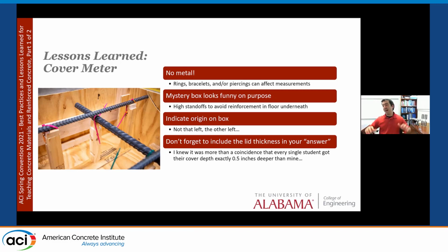Now, this mystery box, it's funny on purpose, like the bars are really high up in the box on purpose. You're going to put this on some surface, likely a concrete floor. It may have vinyl on it, but there's concrete underneath. You don't want the rebar in the concrete floor to influence your measurements.